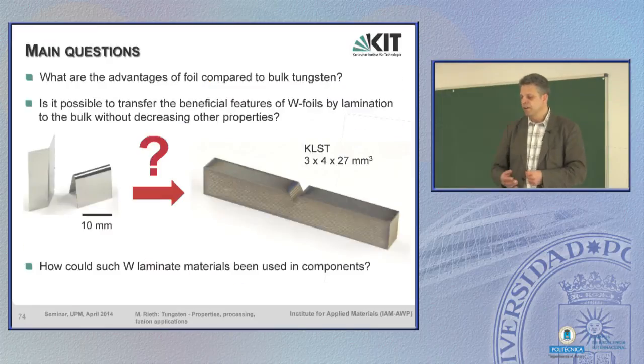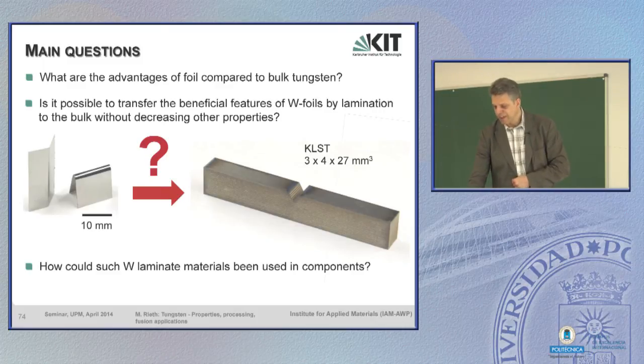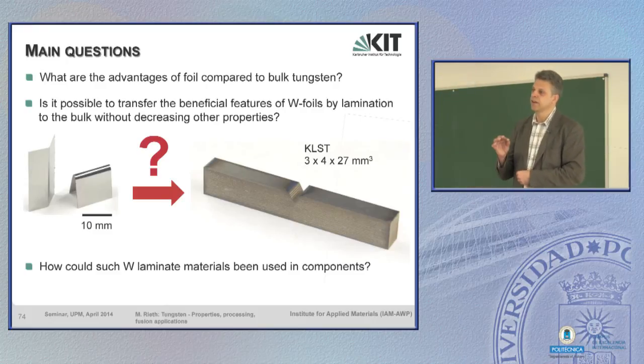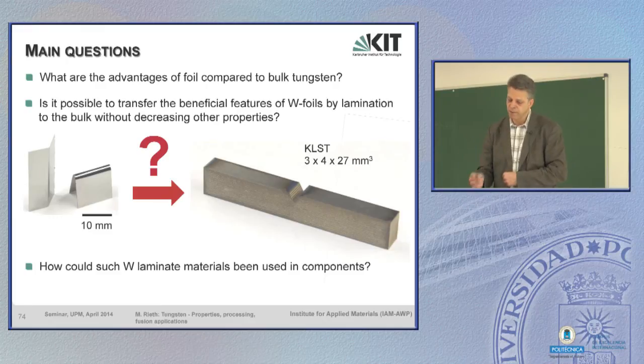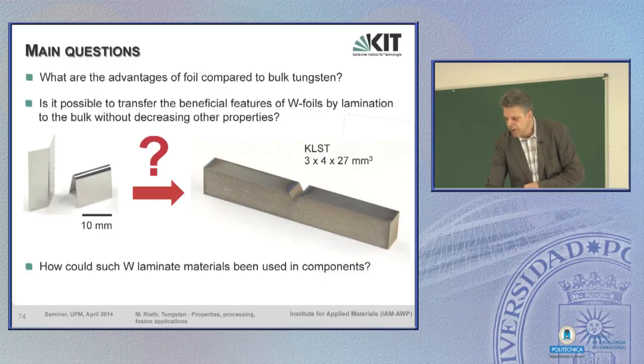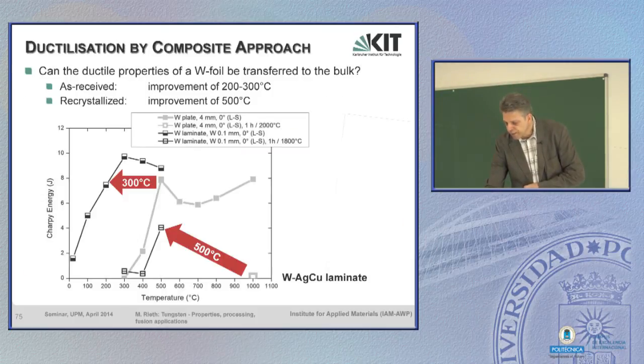The main question: what are the advantages of foil compared to bulk tungsten? And we investigated layered foils to preserve this ductile behavior, and tried to receive some benefit out of this. In the case of Charpy specimens, first have a look at this curve. That's the best available plates we have tested. This is a 4mm plate, and DBTT was around between 400 and 500 C.